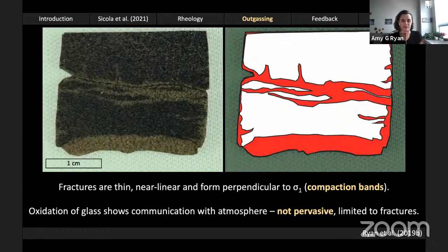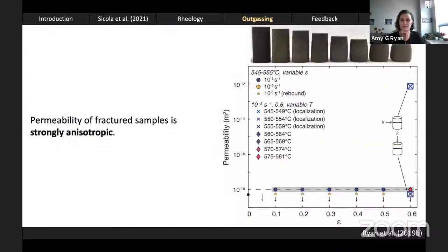Notably, permeability of these samples is also strongly anisotropic. So the 2 data points that you were seeing earlier are actually representative of permeability being measured along the plane of the fracture compared to perpendicular to the plane of the fracture, where the material, the core itself, again, appears impermeable despite having this fracture running through it at the center.